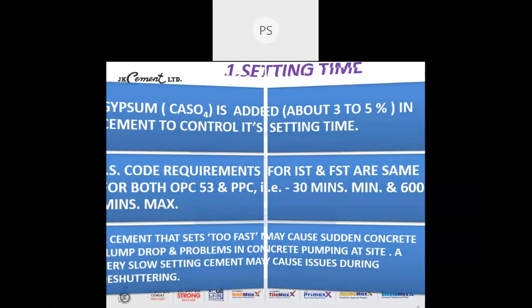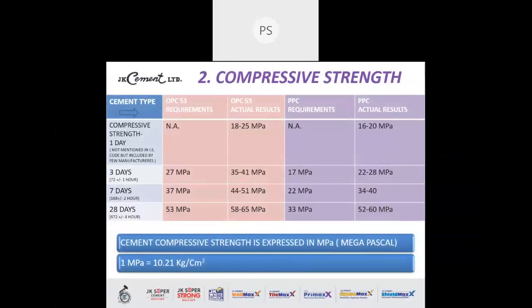Now, second important point is the compressive strength. Compressive strength is measured as per IS code for 3, 7 and 28 days. Few cement companies also mention 1 day strength to highlight their high 1 day strength. Now, OPC 53 requirements: NA, not available for 1 day. OPC 53 actual results in India are between 18 to 25 MPa.